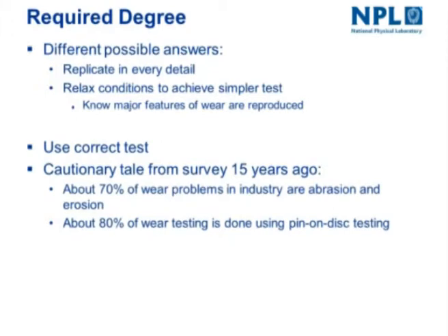It's very important to use the correct test to do this, and there's a cautionary tale here. We did a survey about 15 years ago and found that about 70% of the wear problems in industry, and this is a very broad brush, are abrasion and erosion. It's surprising, therefore, that about 80% of wear testing, as published in the literature, is done using pin-on-disc testing. And even where you've got sliding wear, pin-on-disc testing is probably not the right approach to use. Reciprocating backwards and forwards motion is probably better than the uniaxial, always in the same direction motion that you get with pin-on-disc testing.